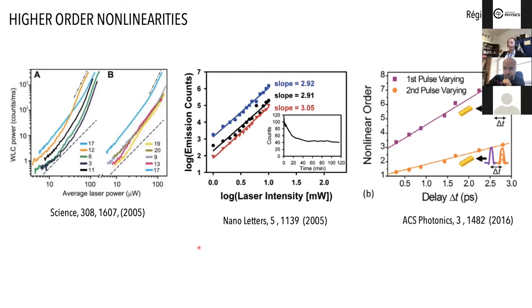Okay, so you get this paper from Bert Hecht back in 2005, where he showed evidence for this broadband emission up to a nonlinearity order of 4. Okay, so 4 photons involved. And you see in this 2005 paper that the slope might not be an integer number. You may have non-integer numbers, of course, this is close to 3, but I think these non-integer numbers were very worrisome in the context of this two-photon absorption or multi-photon absorption.